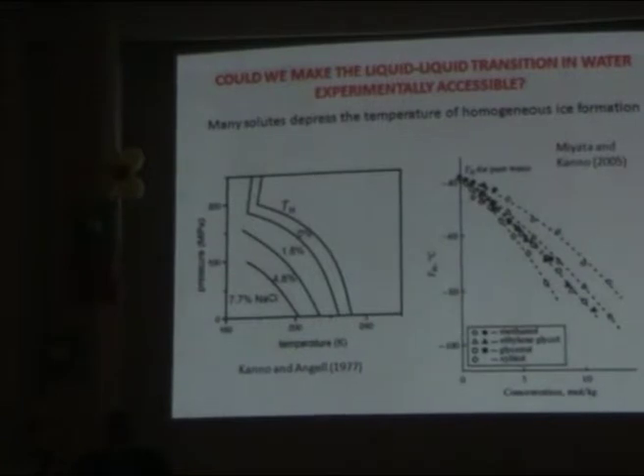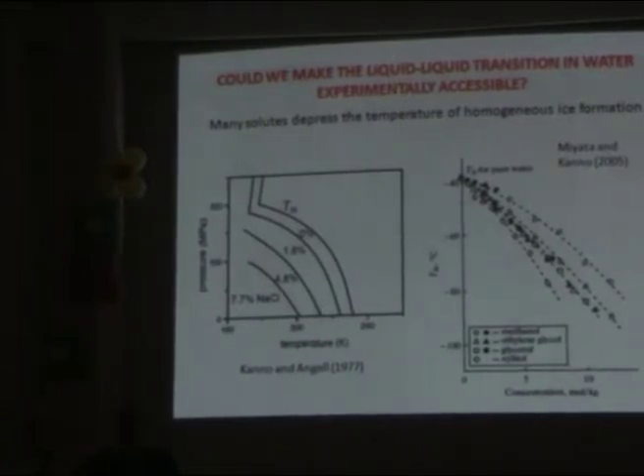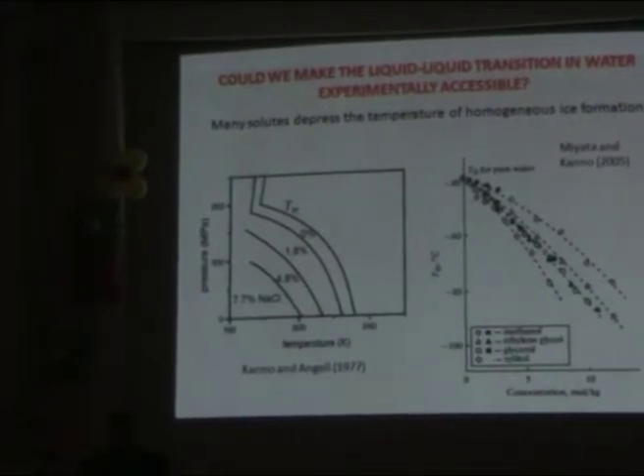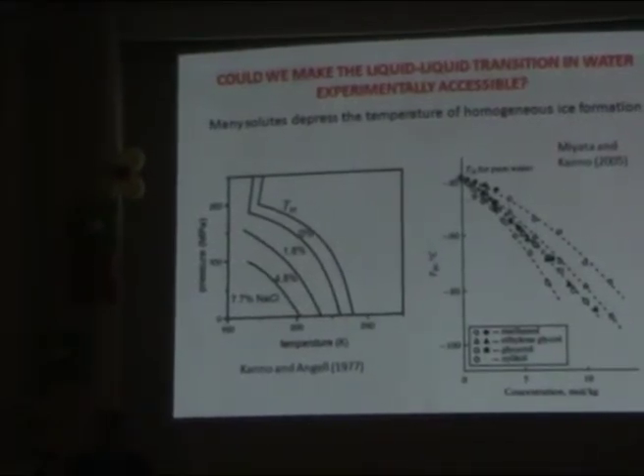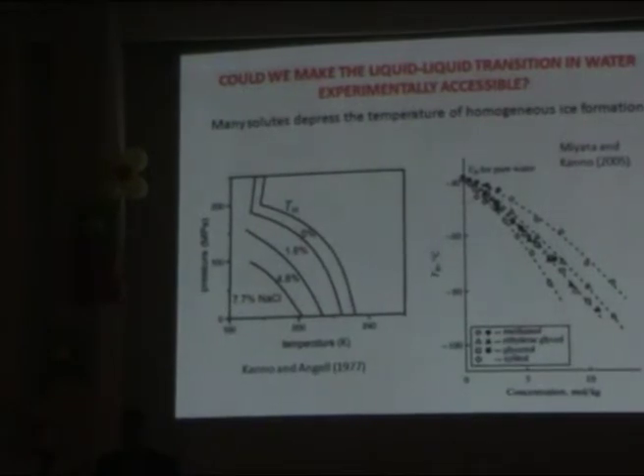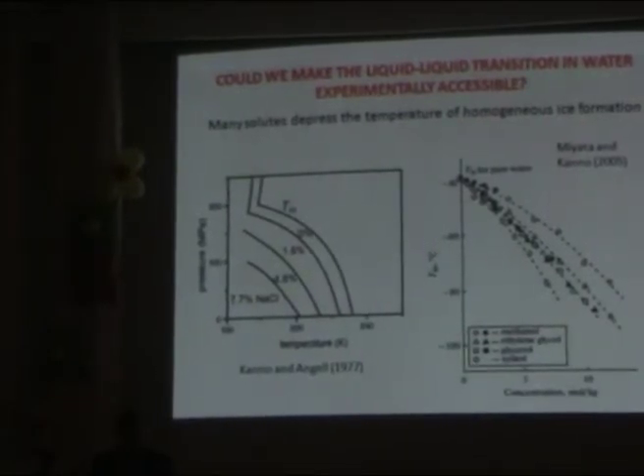If there is a possibility to discover the liquid-liquid transition in pure water, if we add a solute, and maybe if we find a proper solute which could pull the phase transition line and the critical point to an experimentally accessible range of temperatures and pressures, maybe we could directly observe the phase transition in this aqueous solution. And this phase transition would originate from the liquid-liquid transition in pure water.